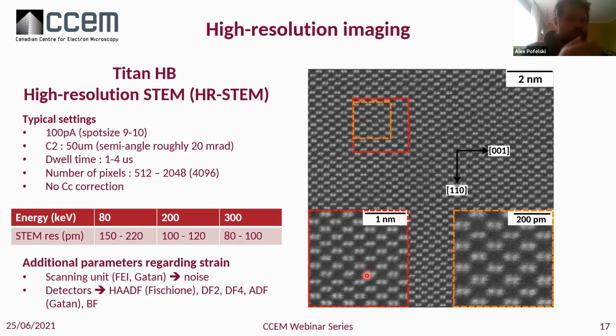So like 100 picoamps regarding the intensity, spot size 9 or 10, a C2 of 50, a semi-angle of roughly 20 milliradians, nothing very special. A dwell time between 1 to 4 microseconds. These are adjustments that will depend on the noise on the day. The number of pixels, 512 to 2048. There is an option to go to 4096, giving a huge data set. It can be used, but most of the time nobody is using it.